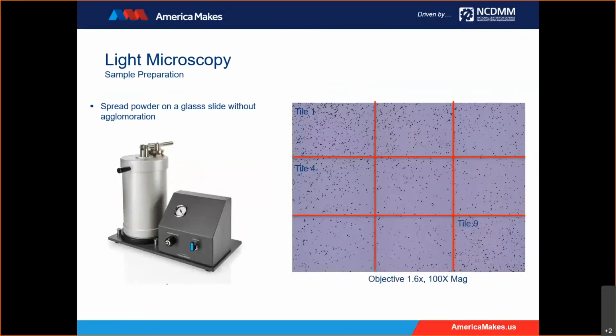The first step to getting good data is sample preparation. What's important is that we spread our powder on a glass slide without agglomeration. We use a powder spreader where you place a substrate inside a pressurized chamber and evacuate the chamber, and then you place your powder particles on top. When you depress the plunger, the pressure difference between the atmosphere and the chamber causes the powder particles to be pulled inside. After a few seconds of settling, we can see a good distribution of our powder over the glass substrate.